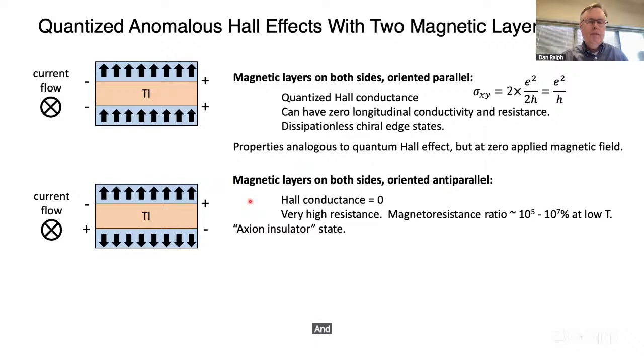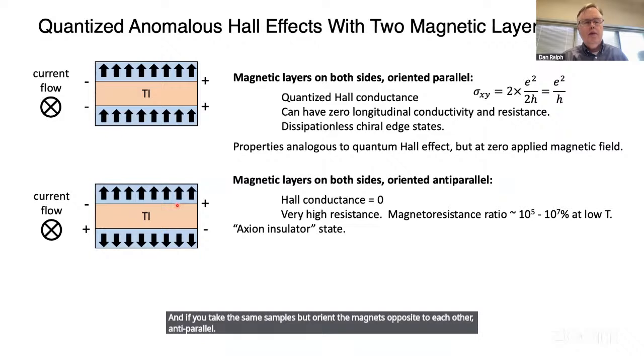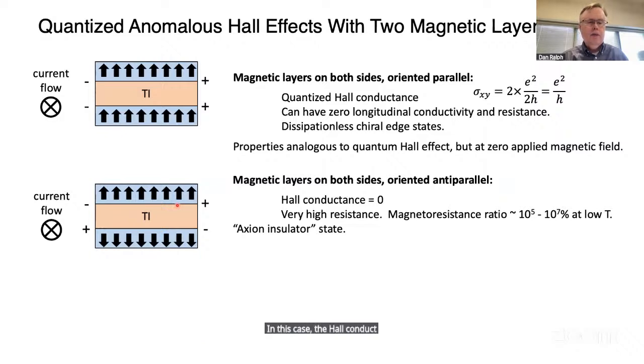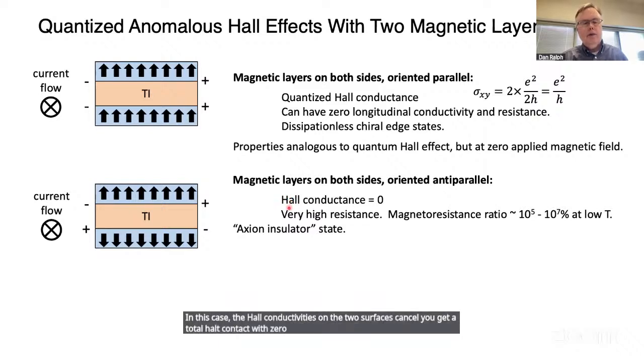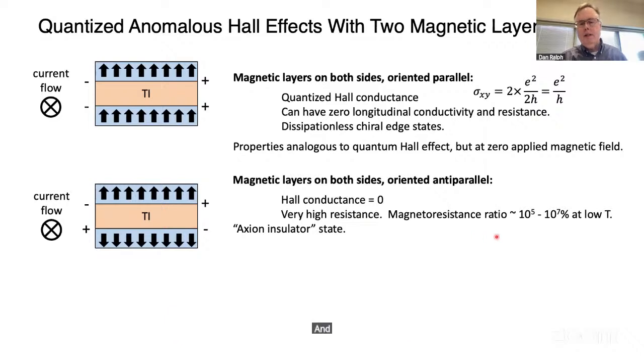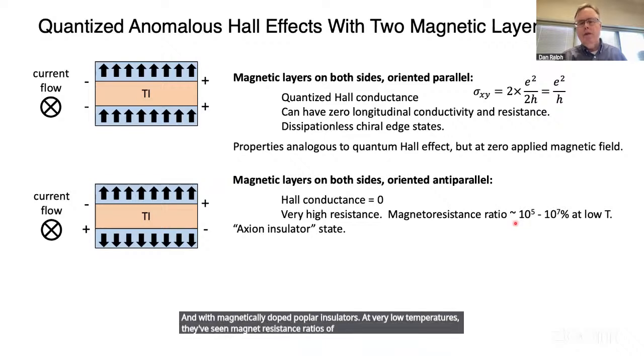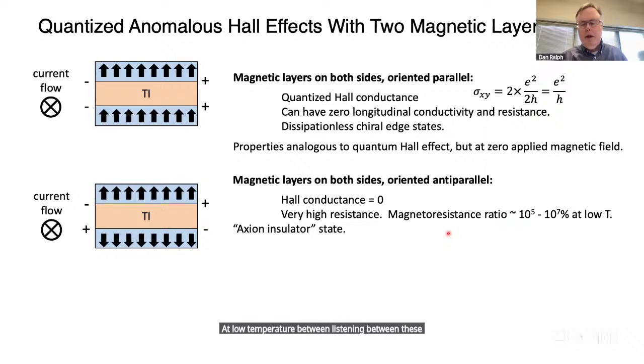If you take the same samples but orient the magnets opposite to each other, anti-parallel, in this case, the Hall conductivities on the two surfaces cancel. You get a total Hall conductivity of 0. And you also get what's been seen, a very high resistance, because in this situation, you quench the edge states. And so there's no particular way of getting longitudinal current through the sample. And with magnetically doped topological insulators at very low temperatures, they've seen magnetoresistance ratios of over 10^5% at low temperature switching between these parallel and anti-parallel orientations.